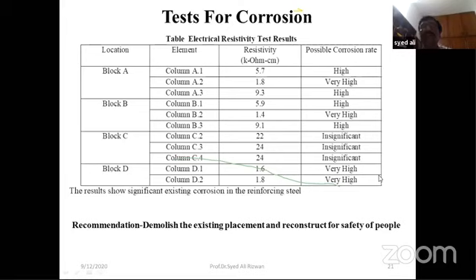Then we measured possible corrosion rates by electrical resistivity tests. Electrical resistivity in kilo ohms centimeter, the readings are this, and the corresponding degrees of corrosion rates are high, very high, high, very high, insignificant, very high. So a combined class of corrosion resulting out of lower concrete grade. So the recommendation was to demolish the existing placement and reconstruct in the larger interest and safety of the people. So the project was demolished.